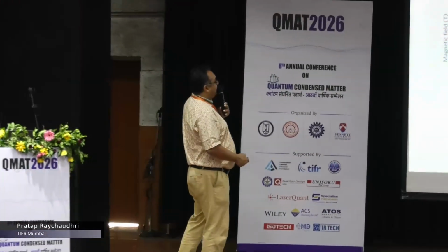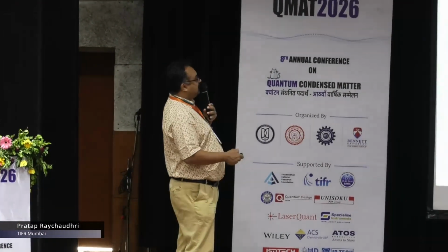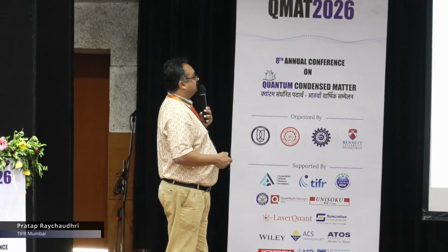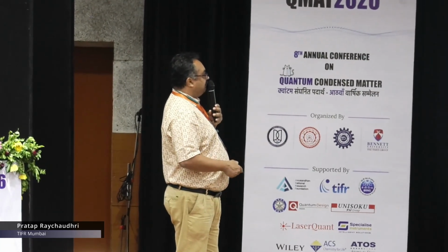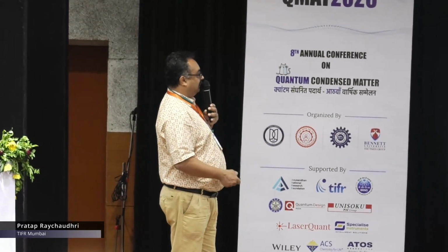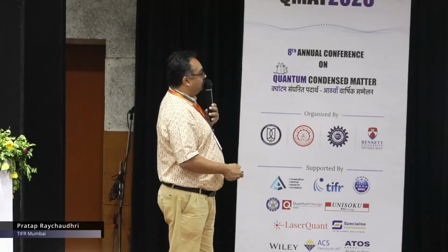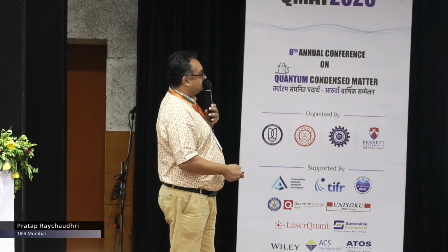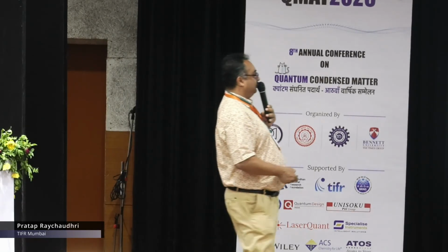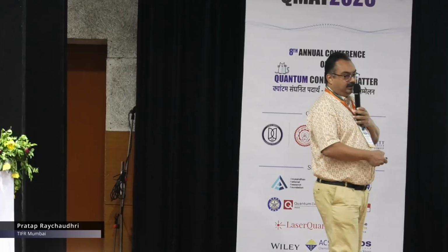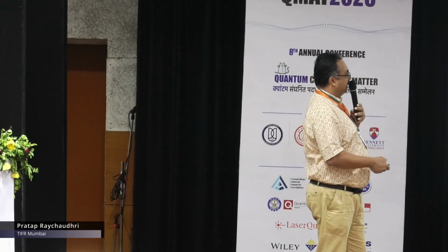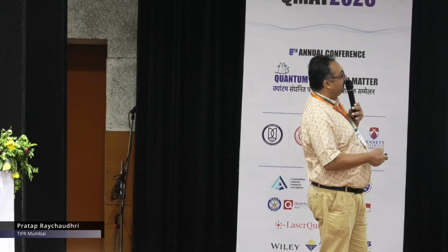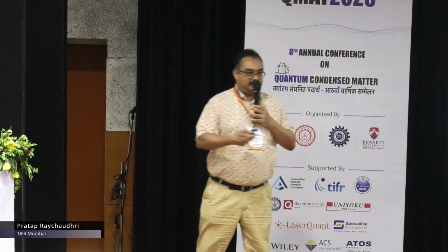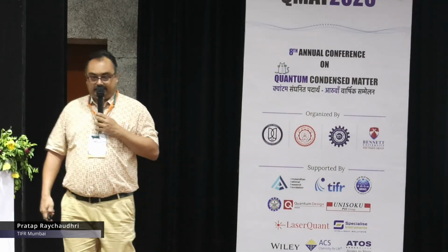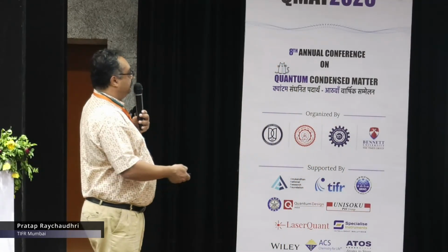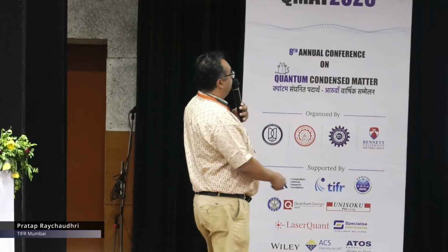But also, the hexatic state is not the only state that has been seen. Some years back, these authors had reported a state which looked like a smectic vortex liquid. However, these images were at that time performed on a small area, and therefore probably these results need to be further investigated in future. So this was on amorphous tungsten films.